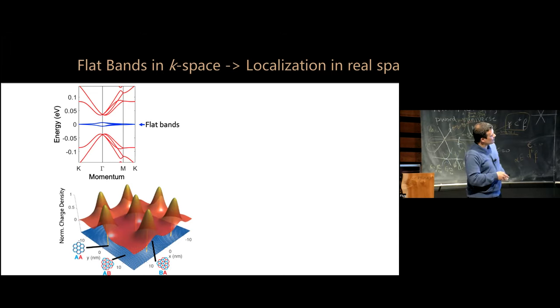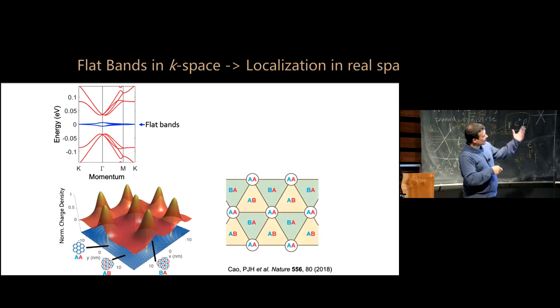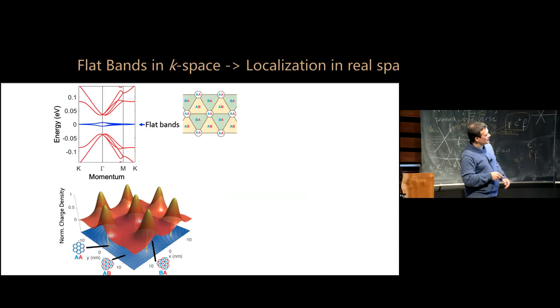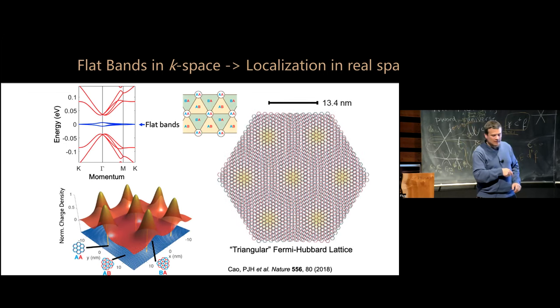So it turns out that magic angle graphene schematically looks like this. There are these regions of AA stacking where all of the carbon atoms on the two layers are on top of each other, and the electrons like to be there. And there are these AB/BA regions where the electrons do not like to be. The more realistic schematic, this is what magic angle graphene looks like.